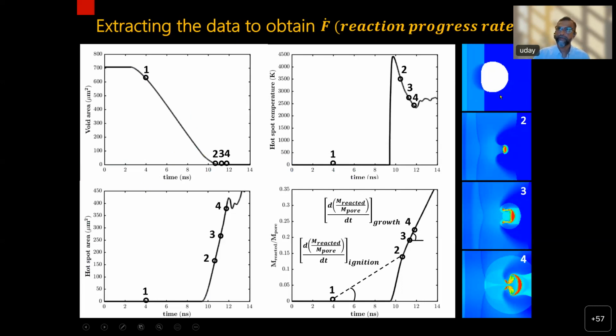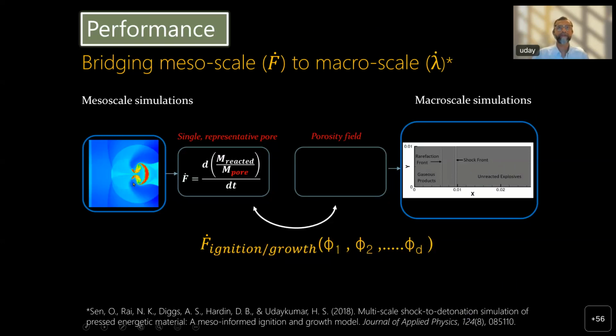Initially, when the pore collapses, you form this ignition. It ignites the material around it, and so that's the ignition phase between 1 and 2. Then that ignited hotspot, if it survives, if it is critical, will grow, and when it's in the steady state growth phase, we take the growth rate. So that's how we get the F dot ignition and F dot growth. Once we have these, in order to close the macro scale simulation, all we have to do is multiply the F dot ignition and growth by the porosity of the material, and then we get what the macro scale requires, which is the lambda dot ignition and lambda dot growth. Again, those mean exactly the same things as in Tarver's ignition and growth model. So we plugged into the ignition and growth modeling framework essentially.